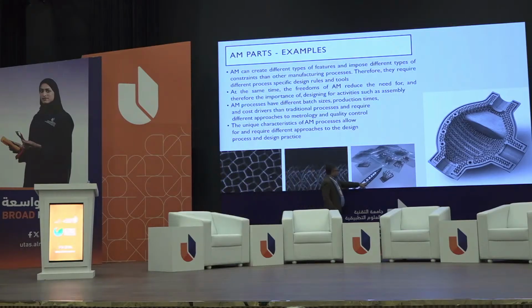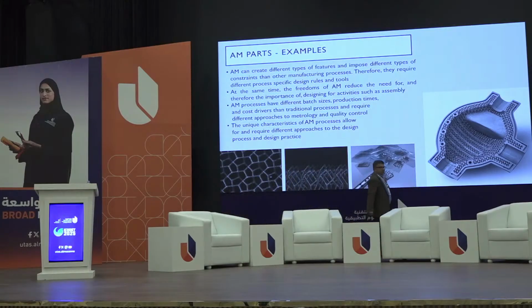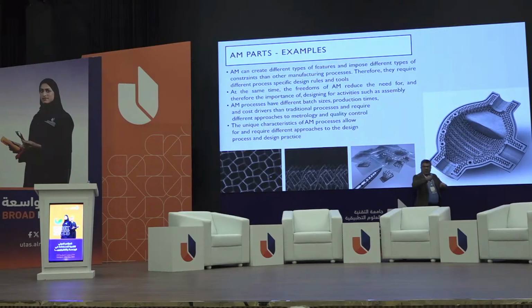Number two, this is 300 micron diameter, each wire of them. They cannot stand the cutting and mechanical forces of the milling machine. Even if you inject them in injection molding, maybe you can do this part, but there's no way you can do this part. Imagine this part, when it was printed, it was sliced. So in each layer, the laser melts wherever, in these selective locations. So for materials difficult to machine, we can do them here, and complex geometry.